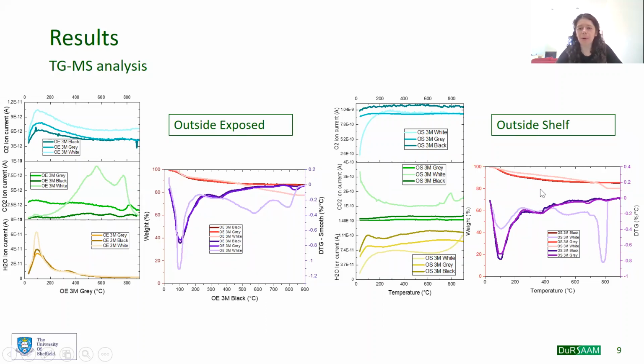The main difference between the sample outside protected from the rain and the sample outside exposed to the rain is that we cannot find much aragonite or vaterite, which is probably because the sample had the time to carbonate properly, whereas for the sample exposed to the rain, there was too much water. And we can see that the peak of water within the carbonated part, the white part, was really high, which is probably due to the free water within the sample, while for the sample outside under the shelf, the water loss due to the CASH phase is lower, which is probably because the CASH has been decalcified by the carbon dioxide.